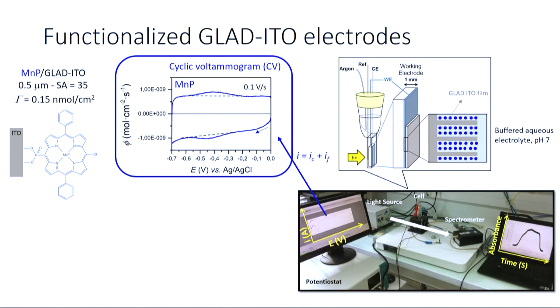And we use a very simple setup, and I want to emphasize this, that spectroelectrochemistry can be very easy to operate, because in this specific case, we just modify a classical UV-visible absorption cuvette to enter a 3-electrode setup inside. And we work in the transmission mode, and so we simultaneously record the electrochemical information and the spectroscopic trace of the immobilized chromophore. And this is a real-time methodology with a millisecond time resolution.